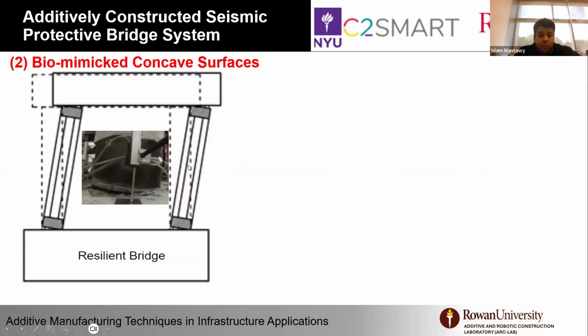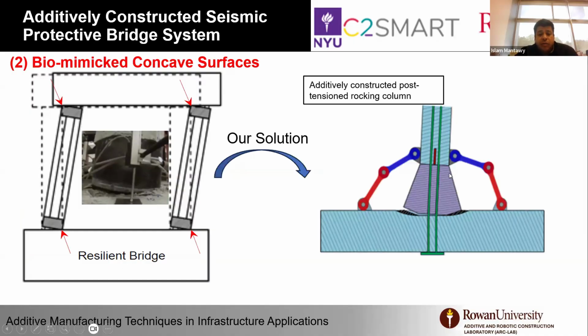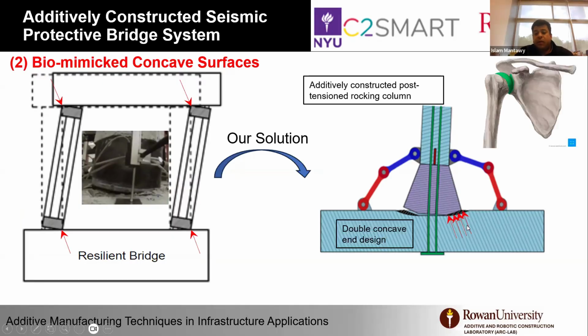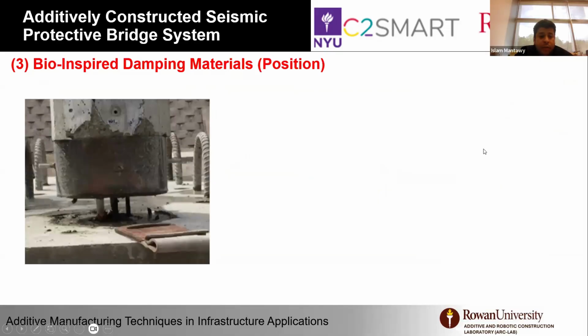During the rocking motion, the structure always tips on four points because of the cylinder design. So that imposes a tremendous amount of stress on the foundation and the bent cap. And we changed that design using 3D printing and the ability to print layered elements with different concave shapes that enable us to create a surface as a trough rather than a concentrated point, which is actually what we have in our body too. The ability to dissipate energy instead of permanent damage of rebar inside that warrants total replacement.